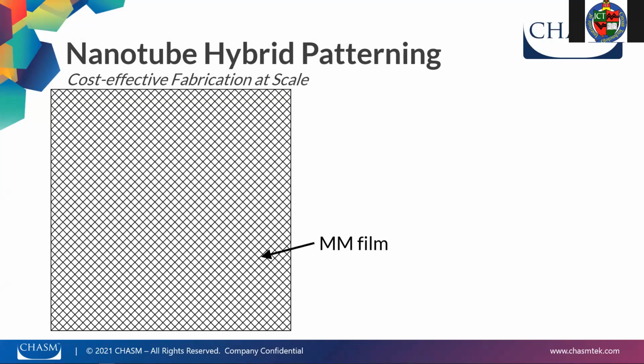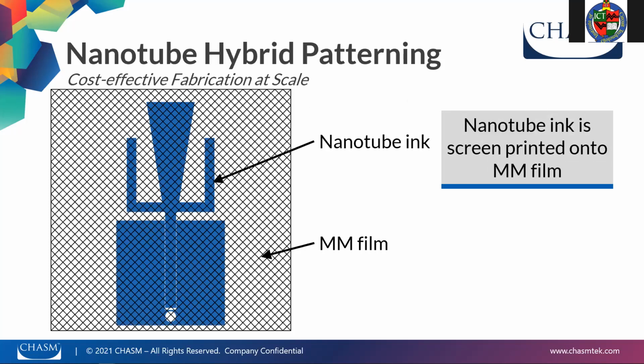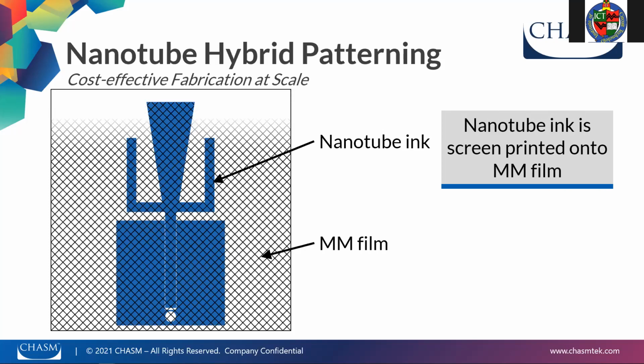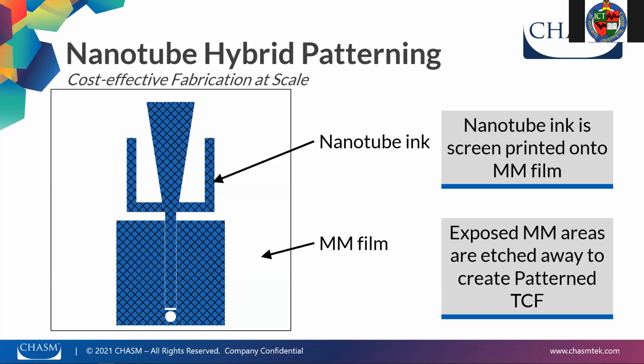So how do you go and make a circuit out of a nanotube hybrid? Unlike the commercial alternatives that require either laser ablation or photolithographic etching, which are both expensive and time-consuming, nanotube hybrids are patterned using inexpensive and readily available screen printing techniques. So you start with a film, in this case, a metal mesh film. You then use standard screen printing techniques to print the shape of the desired antenna that you want, in this case, a monopole antenna. These can be repeated multiple times, so you can really cost effectively gang together and tile many circuits onto one sheet. Then a simple wet etching process will remove any of the exposed metal mesh areas that aren't desired, and you're left with the patterned TCF circuit in the desired shape that you would like.